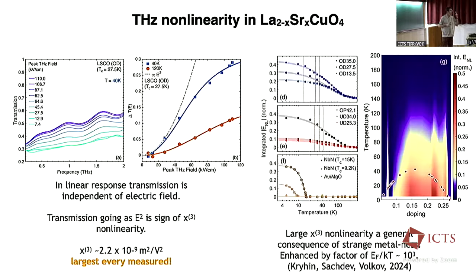So a normal metal with parabolic bands and elastic scattering has no nonlinearities. There's essentially two ways that a metal can be nonlinear at low frequencies. It can have very non-parabolic bands, and that's like the case of graphene. And graphene was previously the largest nonlinearity that anybody knew. Or it can have very large inelastic scattering, or if you will, energy-dependent scattering. And so cuprates, of course, have very large inelastic scattering. And this is what we think is going on in the system here. And Avishkar and Subir Sachdev have a paper on this.